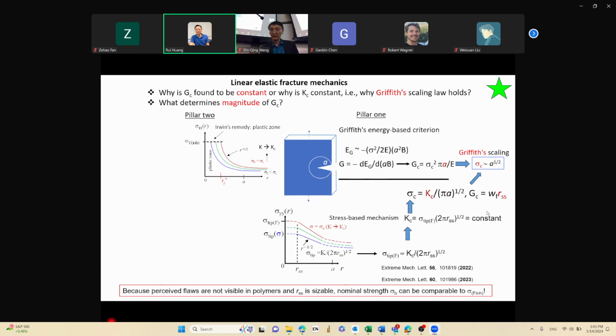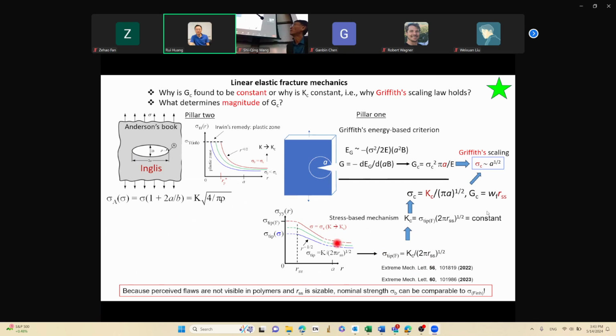of 1913 of Inglis. By the way, this scenario by Irwin directly contradicts Inglis's result. Inglis told us the tip stress should just linearly increase with load. And this does not have that scenario at all. Moreover, push this all the way to the point of fracture. K, of course, becomes Kc, this magic operational definition. But on the left, it tells me what is the material definition of Kc, because that's when the left reaches the strength.